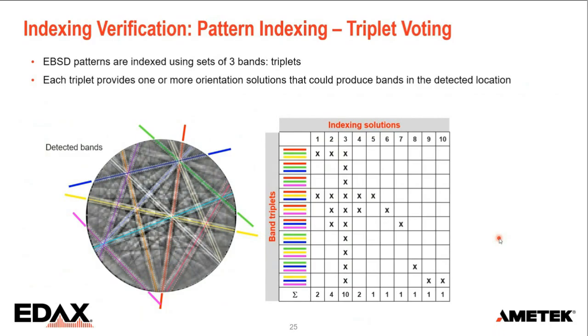For that, I want to quickly go to the indexing algorithm, what we call triplet voting, because that is what tells us not only what the orientation is that we can extract from a pattern, it also tells us if there's more than one possibility for an indexing solution. So we can put a measure on how sure we are that we have a unique solution. And we do that by specifying triangles or triplets. For each triplet, we can identify an orientation, in some cases more. So here I've got 3 orientations for this triangle. Here's only 1, etc. And in the end, we have a table with all the possible orientations. And for each orientation, we have a number of triangles or triplets that match it.